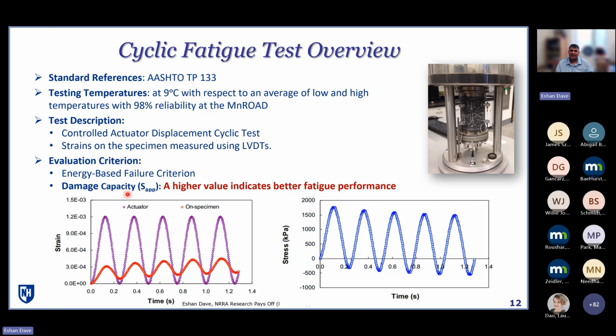So there is again a damage-based index that has been proposed, and Federal Highways has conducted a validation of this index. It's called S apparent, or Sapp, as people often refer to it. With this index, once again, typically you want a higher number to have better fatigue performance. But keep in mind that this is a reflective cracking study.